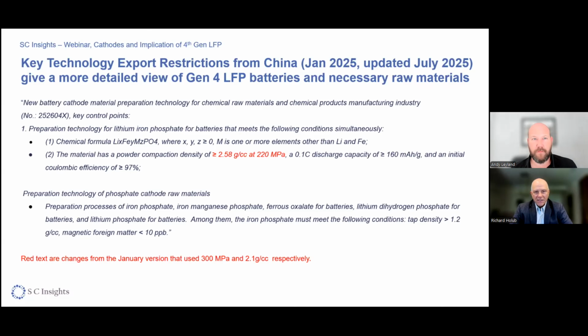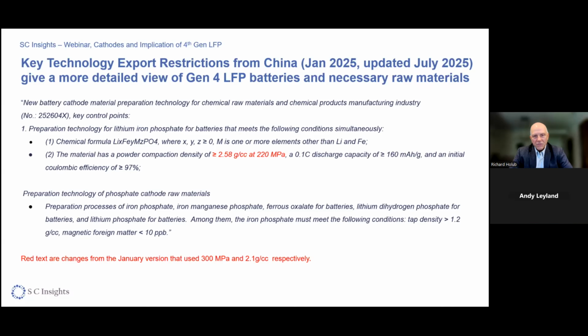So it says the compaction density of the powder has to be greater than 2.58, a little bit more specific now, not the 2.6 you see in press releases. And also 220 megapascals of pressure are key things, and that it also gives a discharge capacity at effectively 0.1C and an initial recharge, or Coulombic efficiency, of greater than 97%. So that's what, at least in the technology arena, the folks in China believe are the critical things.